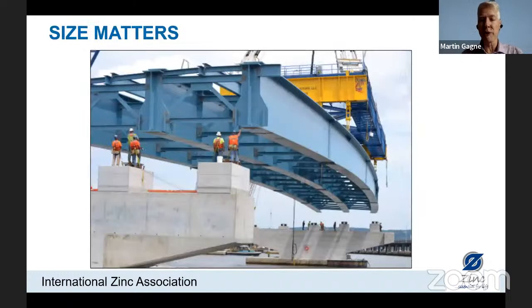And here's an example of a bridge structure. I will be giving examples from North America, primarily where I'm based, and referring to North American standards. But we can see here the main structural beams of this bridge are too large to be hot dip galvanized. But all the cross bracing and support members and also the hardware could be hot dip galvanized. And if we thermal spray the beam and we hot dip galvanize the cross bracings, when we assemble the bridge components, we have zinc metal in contact with zinc metal. There's no potential for bimetallic corrosion.